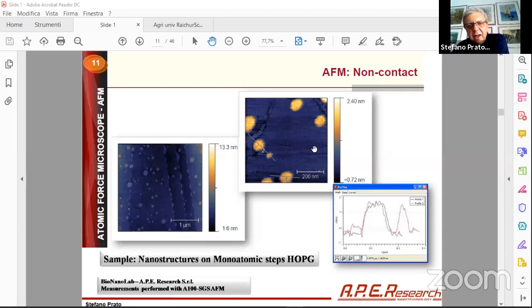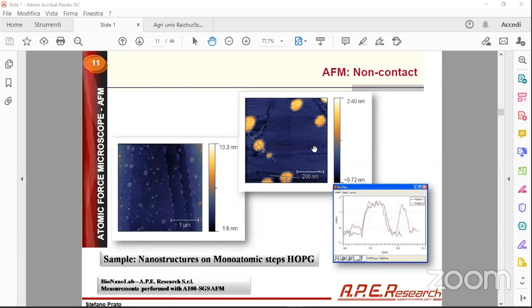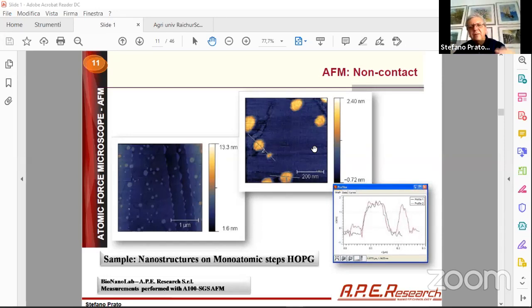With AFM this is very important, because it's not so easy to resolve those. First of all, because of the resolution, because those particles are quite small. With other techniques, it's not so easy to watch them. For example, if you use an electron microscope, you will bombard them with electrons, so you will eat up those molecules, which will blow away and evaporate. For some material, mainly organic material, it's very important to have the resolution, but I will talk later about the sensitivity. In this case, it is so-called non-contact AFM. So we are not touching the surface. This is very important, as it will preserve the material from being degraded.